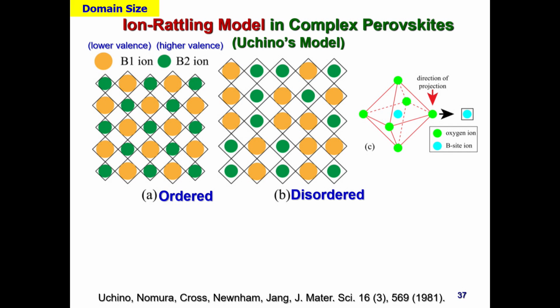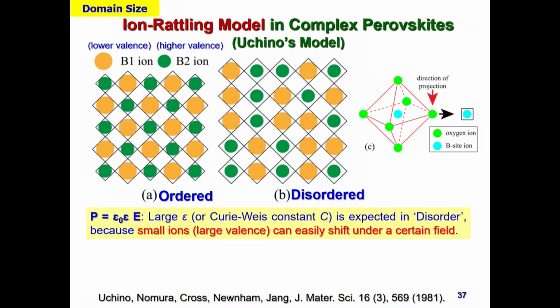So ordered, disordered. We presented the ion rattling model at that time. So you don't need to consider any polarized state. This is like a dipole, you know, just the paraelectric state. Ordered, disordered, what's the difference? How about the Curie constant or the permittivity? In that case, we apply some certain electric field. So here, disordered, you can find a smaller ion that has usually a large valence, is easily moving without distorting any, you know, this frame. Therefore, much larger permittivity is obtained. So the disordered should create a larger Curie-Weiss constant.